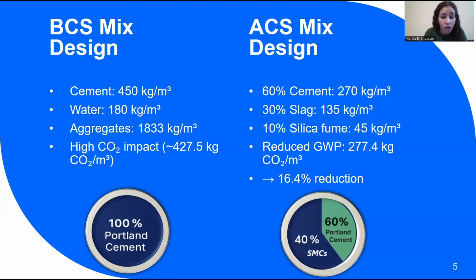As we know, cement alone made up a large percentage of the environmental impact, about 75% of total emissions in this mix. So we did the ACS mix design to make the mix more sustainable. We replaced 40% of the cement with two supplementary cementitious materials, 30% slag, which equals 135 kilograms per cubic meter, and 10% silica fume, equal to 45 kilograms per cubic meter. That means the binder in the ACS is only 60% Portland cement, and these materials are industrial byproducts that have a much lower carbon footprint compared to cement. Slag is a byproduct from steel manufacturing, and silica fume comes from the production of silicon. By using them, we not only cut emissions, but also reused waste materials.